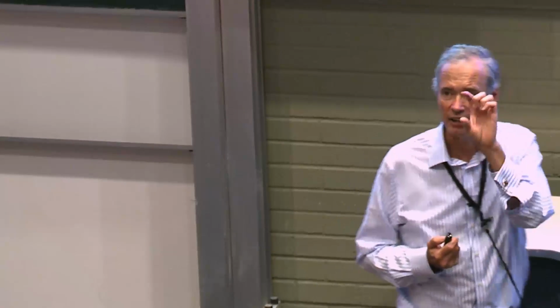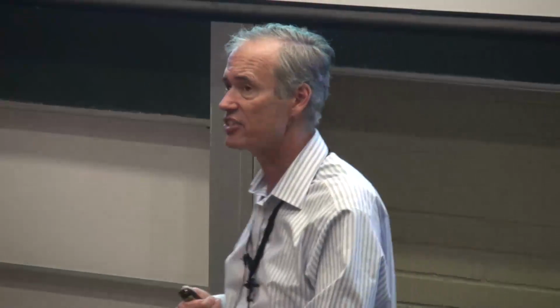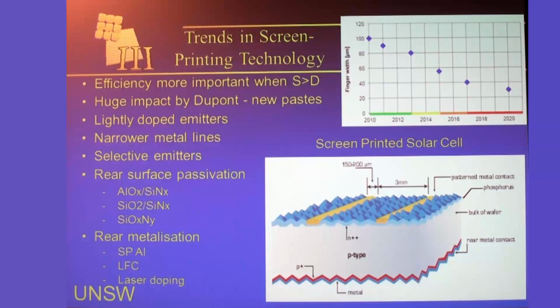They're narrower and you can also print higher. And so that's enabling them to retain the cross-sectional area of the metal lines, but simultaneously reduce the shading losses. So DuPont has made big contributions. And so only a few years ago, typical screen-printed solar cells on Czochralski wafers were around 16.5% efficiency. Now they've jumped to about 18.5% efficiency, just thanks to DuPont and the developments that they have made.